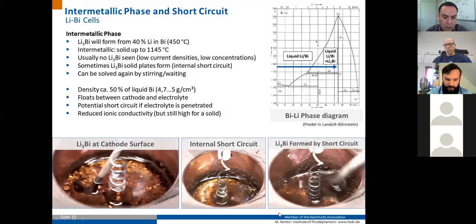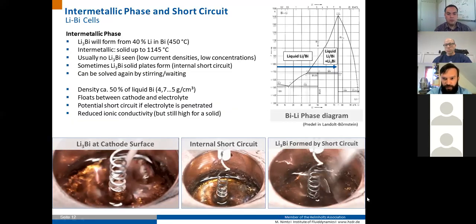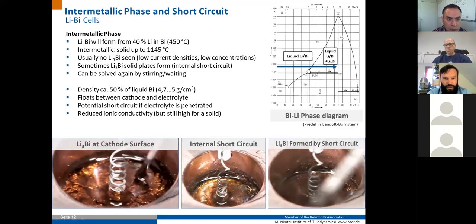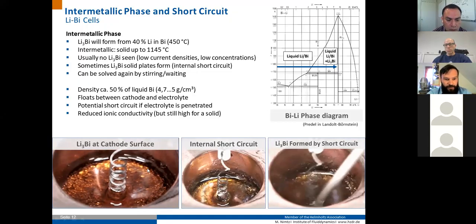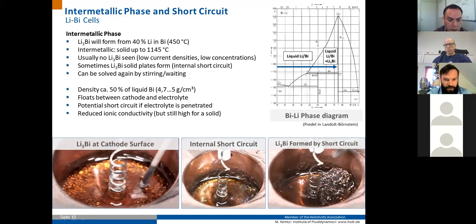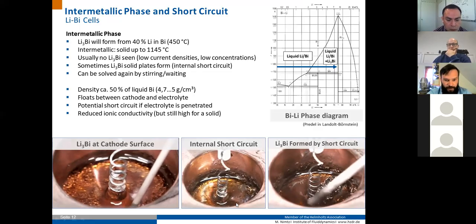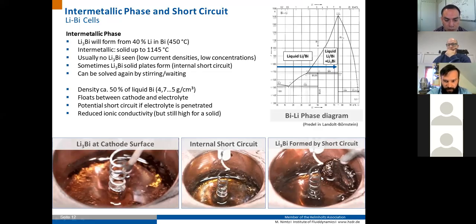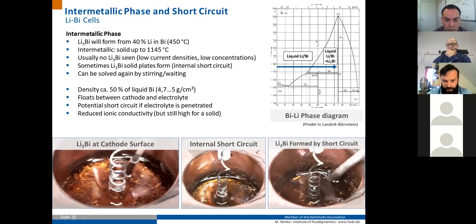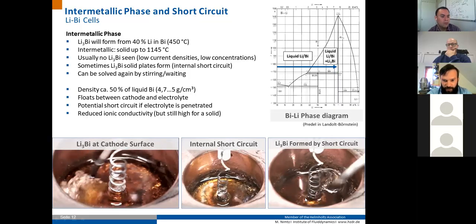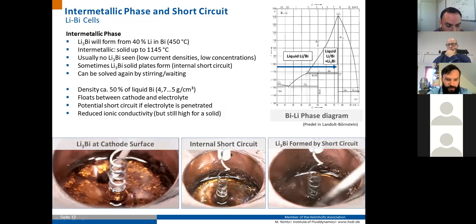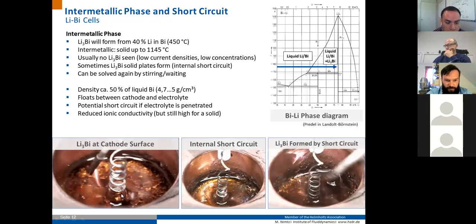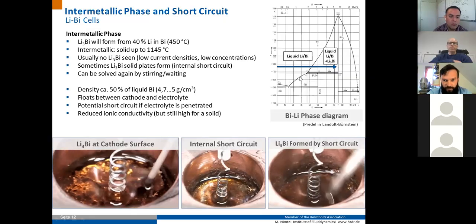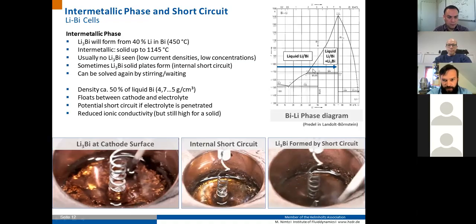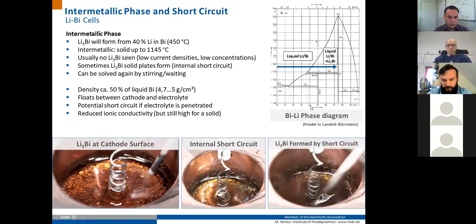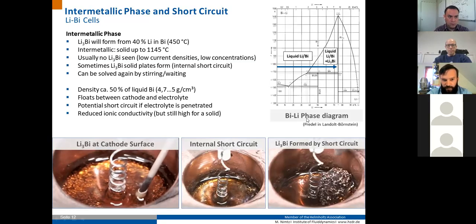You can only remove it by adding more bismuth to lower the concentration of lithium again. If a short circuit occurs, typically all the lithium is reacting with the bismuth at the surface of the bismuth electrode, forming such a Li3Bi disk, which is then solid and takes some time to dissolve again. Typically, the cells are constructed so that the amounts of lithium and bismuth do not reach the full solid region. It's typically so that we roughly reach the liquidus line here, which means about 40% lithium if we mix lithium and bismuth completely.